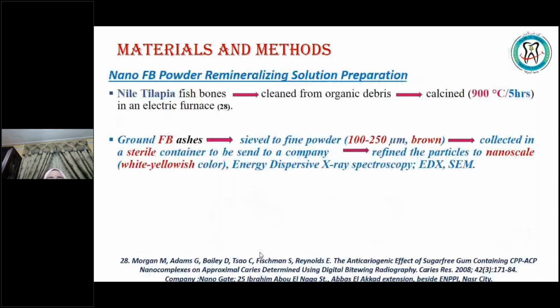How was the nano fish bone powder remineralizing solution prepared? First of all, the Nile tilapia fish bone was extracted and separated from the organic materials, then cleaned and dried at room temperature. Then it was calcined at 900 degrees centigrade for 5 hours in an electric furnace. Then the ground ashes of the fish bone were sieved to a powder size of 100 to 250 micrometers. At that time we noted that the color of the particles was brown.